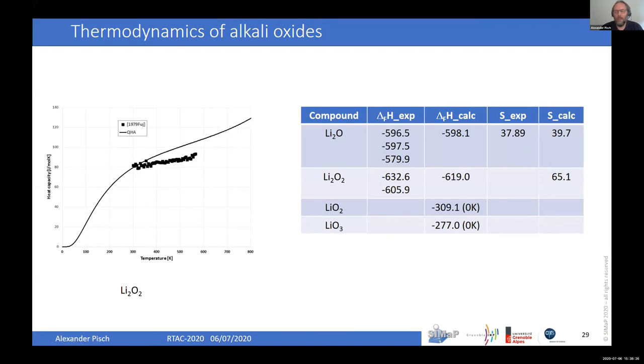And this is also given by the fact that we get a nice value for the heat of formation. Here you see the calculated one. So it's at room temperature, corrected with the zero point energy and heat content. And you see we are basically in very good agreement with two of the reported values. For lithium peroxide, we get a good agreement at room temperature, and then we deviate. Maybe our calculation, maybe the experiments. Again, experiments are very tricky in this case, because the materials are very, very reactive. Our calculated heat of formation is right in the middle between the two experimental values.